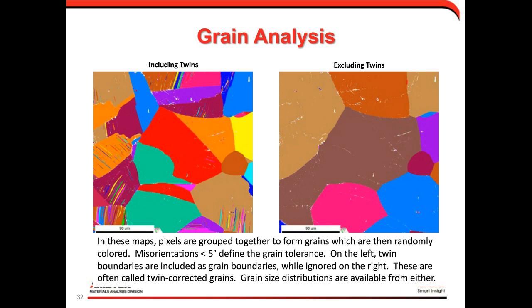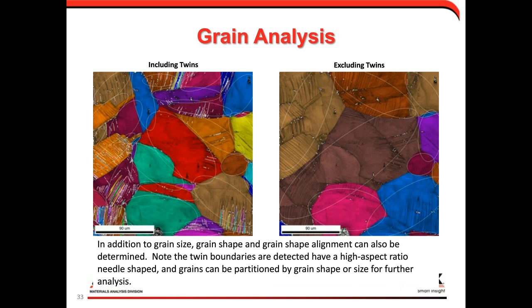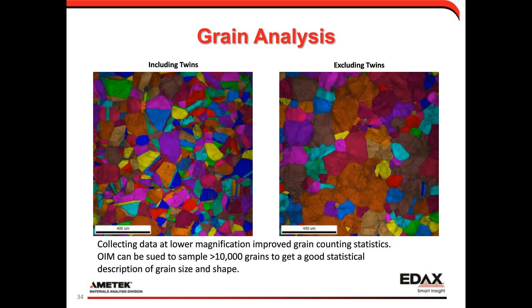And so this shows, and of course, if we go to a lower magnification and we take more measurements, or even a larger area with a coarser step size, we can collect more grains to get a better idea of counting statistics. So this is just an example where we can collect more than 10,000 different grains to get a good statistical distribution of the grain size and shape to sort of quantify a microstructure.